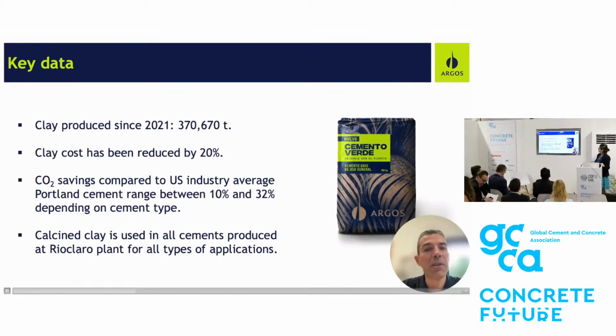These are some of the key figures of our limestone calcined clay plant in Rio Claro. We have produced since 2021 a total of 370,000 tons of calcined clay. The cost of the clay has been reduced by 20% through the ramp-up process, and it is much cheaper than the clinker produced at the same plant. The CO2 savings compared to the US industry average Portland cement range between 10% for the higher clinker, more high performance product, and 32% for the lower clinker products such as bagged cement or general use cement.